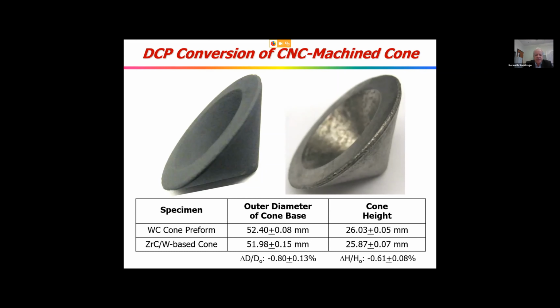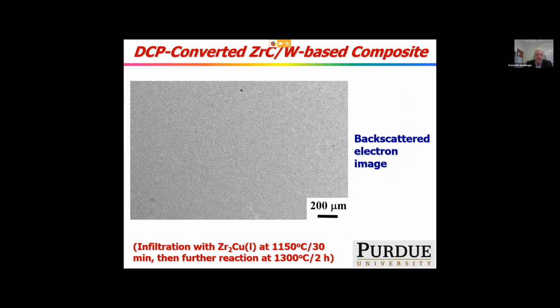From this process, if you cross-section the material, it looks like this at low magnification in the SEM. I should mention these are very difficult materials to cut. If you try to cut this with a diamond wafering blade, it takes a long time. Fortunately, however, these materials are also electrically conductive. And so we typically cut these materials by electrodischarge machining and then polish them. What you see here is a polished low magnification cross-section. You can see a few pores, but not much. Some of that may be pull out from polishing.